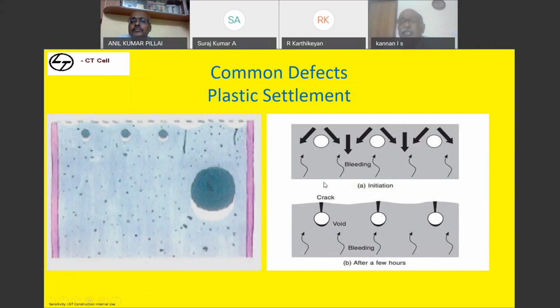Whenever you observe this, don't panic, because this is a natural phenomenon. It can happen if you are using a higher slump of concrete, or where the accumulation of slurry is more during the finish, where the mason has pushed the slurry to one end, or where the cover to the reinforcement bar is less. In such cases, once you see that, place some concrete in that location and revibrate it. That's all, simple. When you revibrate it, you are able to close everything.